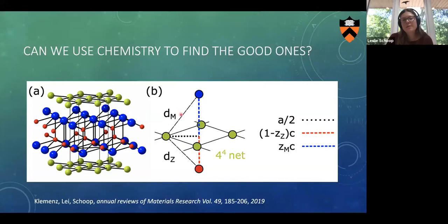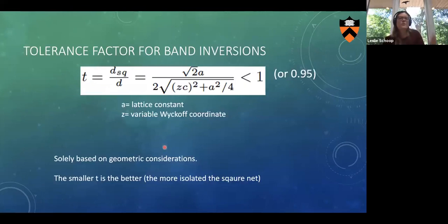And so for this one crystal structure, I could put this in an equation. It's a simple equation. The d square net, this distance, is supposed to be smaller than the other distance. And I could also put that in terms of lattice constants and Wyckoff coordinates, but that only works for each crystal structure individually. And then this should be smaller than one, or later we found maybe a better cutoff parameter is 0.95. And then I should have a hypervalent bond. And then ergo, because of that, I should have linear crossing bands and a topological semi-metal. So let's see how that works.